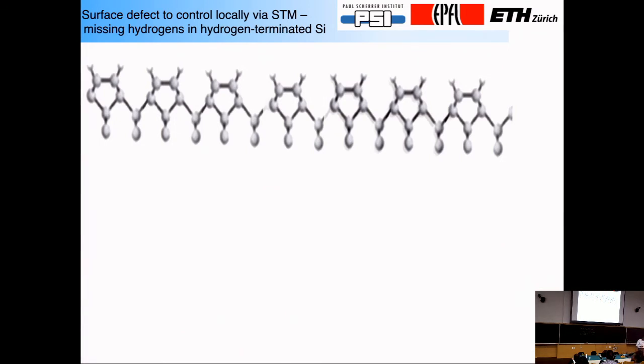To see whether orbitals can be controlled electrically or not, you have to work, at least in the first instance, near a surface where you can actually apply electric fields and see with STM what you're doing. And so as a model system, we looked at the surface analog, essentially, of phosphorus in silicon. And this is going to require a little bit of imagination, but typically, of course, silicon 100, when you cut it, is no longer happy.